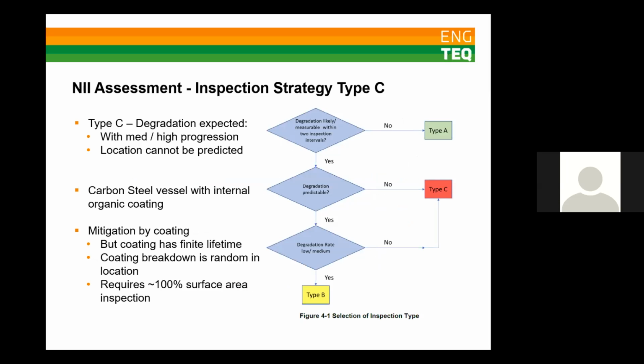The third and final inspection strategy type is a type C. So this is applicable when degradation is expected to be medium to high rate, but the location can't be predicted. And the aim of a Type C inspection is to directly measure the worst area of degradation. So this is typically applicable to carbon steel vessels with an internal organic polymer-based coating. So the coating there protects the carbon steel, but unfortunately, organic coatings have a finite in-service lifetime, and this can be very hard to predict.